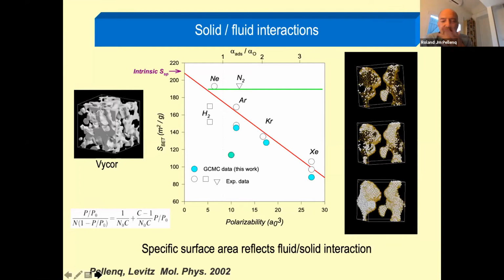Some years ago, with Pierre Levitz, a colleague from Paris, we did this calculation in simulations where we measured specific surface area. We used grand canonical Monte Carlo simulation of very simple fluids, different rare gases—neon, argon, krypton, xenon—into Vycor, which is a porous glass, mesoporous. We were measuring the beginning of the isotherm, so to say we are measuring the surface.